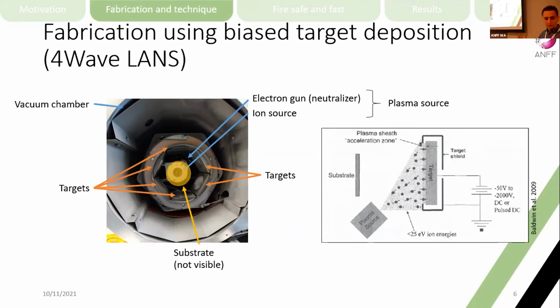So we have a plasma source. This plasma source is emitting a very low energy plasma. And the ions in this plasma have very little energy so that they don't damage the chamber or sputter away any material. The target from which we want to deposit material is then biased with a bias voltage. And when the ions come close to the target, they get accelerated, they gain momentum, they gain enough energy to actually sputter away from the target. The material that gets sputtered away flies through the chamber and lands on our substrate.